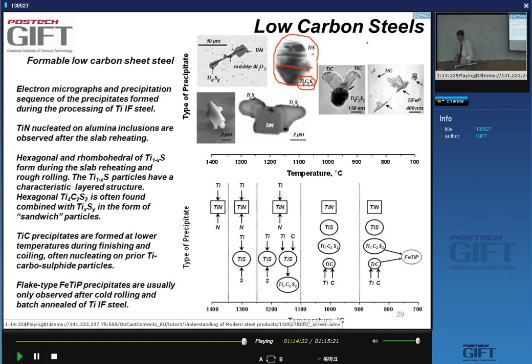So although the IF steels are much more robust in terms of processing, you're still dealing with steels where you have to watch the way you process them. But in principle, whatever the coiling temperature you use, you can process them in a batch annealing furnace or in a continuous annealing furnace. In contrast to the low carbon steels, where you really have to choose the way you're going to anneal them and then pick the right coiling temperature.